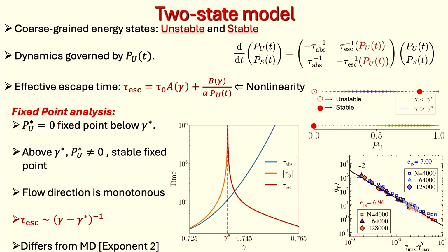what this does is, instead of making the yielding transition only apparent, it actually makes the transition a genuine transition, and it also gives you a divergence of time scales like what we see in simulations, with some problems. The exponent that comes out is not the same as what we see, but we've made so many simplifications that maybe it's a little much to expect everything to come out right, but here it is.